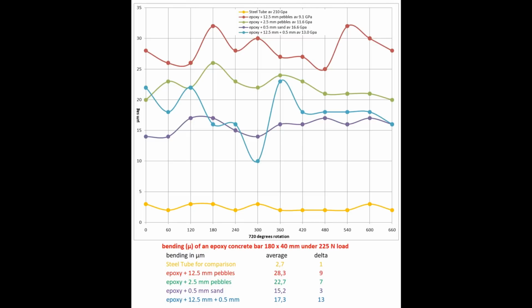This graph gives a clear impression of the resistance to bending of the test bars and how homogeneous the epoxy concrete mixture is. The red line is of the coarse pebbles. This is clearly the least desirable filling, not very homogeneous, and the weakest of all four. The somewhat stronger filling of fine pebbles is also certainly not optimal, as the green line shows. The best result is given by the mixture with the fine sand according to the purple line. This is the most homogeneous and strongest epoxy concrete. The mix of pebbles and sand is even stronger in some places, but is very inhomogeneous.